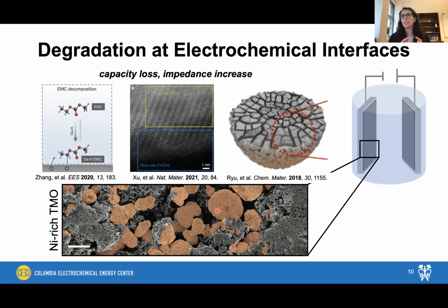So whenever you have these mechanical strains during lithiation and delithiation of this material, the secondary particles undergo cracking. This exposes fresh surface where you can have either electrolyte decomposition or rock salt formation on the surface of the freshly exposed particle surface. So we have two mechanisms here on the right, the rock salt layer formation and the particle cracking that can be readily studied by techniques like electron microscopy. So this is a high resolution TEM image shown here. This is a tomography image shown on the right.